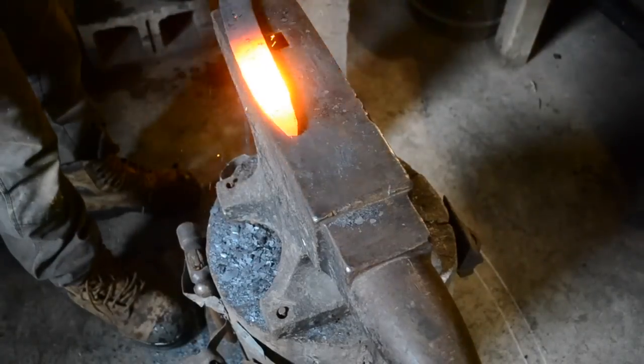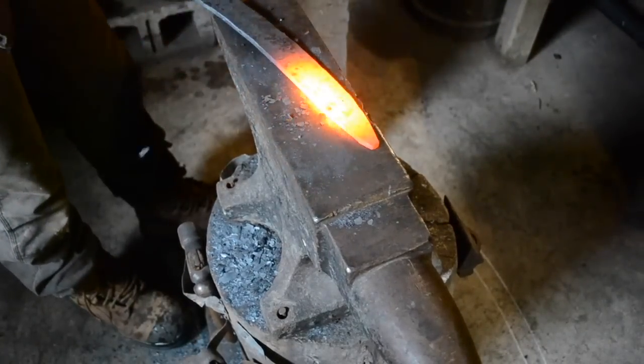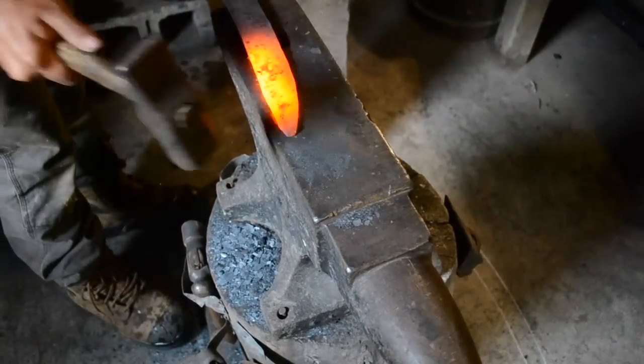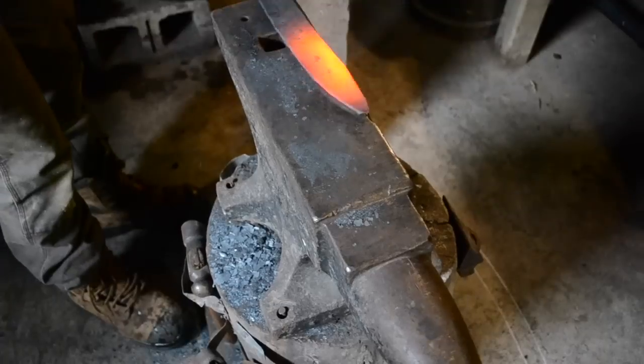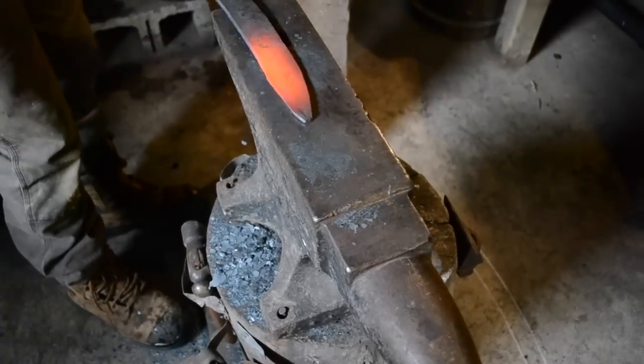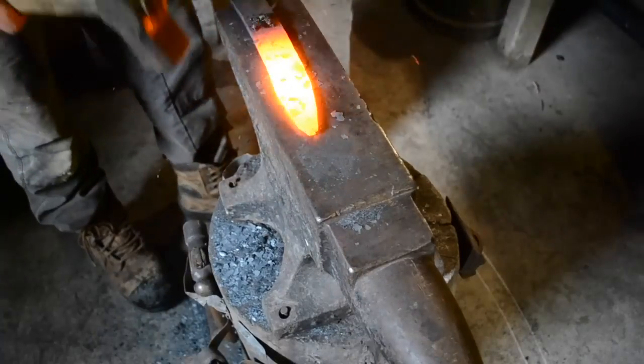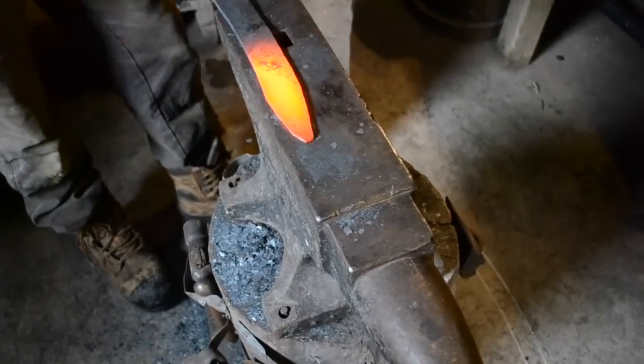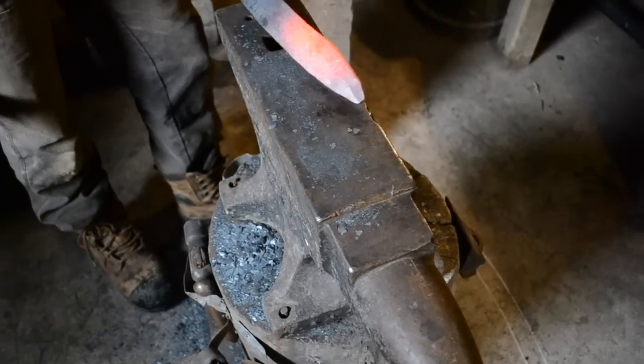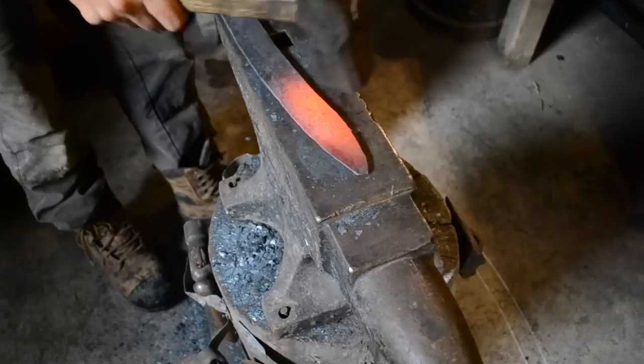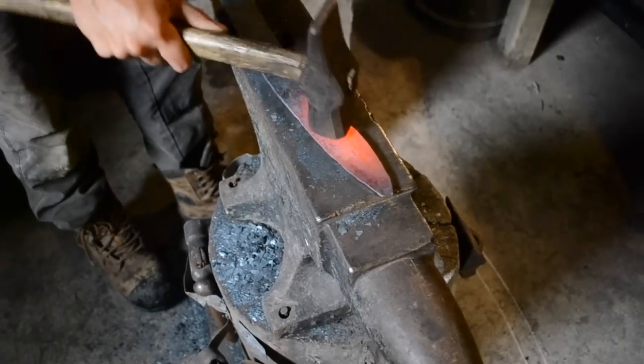The false edge is going to change the angle of the tip slightly, so I'm going to increase the curvature before working on it. Now I start on the false edge, same thing but on the other side. It's very easy to completely screw up the geometry when forging in the false edge, so you want to leave it a little bit thicker and do most of the work on the grinder. The blade started to corkscrew a little bit, so I'm just going to tap it flat. Hit it firmly but not hard.